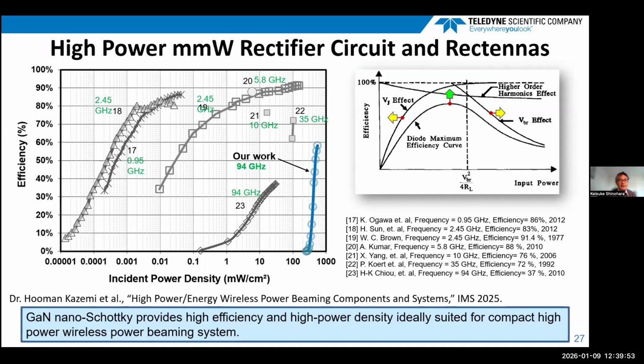On the left, the obtained result of RF to DC conversion efficiency is plotted as a function of incident power density in the blue solid lines in comparison to the previous result. And with our technology, we could obtain more than 50% conversion efficiency at 94 gigahertz with high power density.